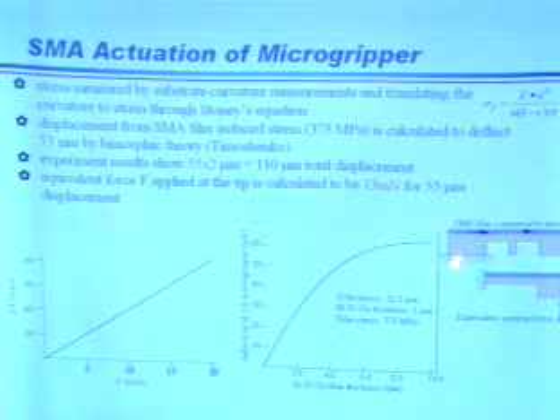Again, this is not a thermal bimorph effect, which the earlier one that I mentioned was. It's a phase transformation effect. So you put the shape memory alloys on top of these cantilevers at high temperature, to 500 degrees actually, and then you anneal it to crystallize it, but have a shape memory effect. As it goes down, the thermal stress allows it to curl up until you hit what they call the martensitic phase, where it becomes soft and allows twin boundaries to have large strains. And then the stiffness of the silicon eventually allows it to bend backwards and become flat again. So that's how it works. When you heat it up, it remembers its original shape, which is a stress state, and then it pulls in and opens up the gripper.